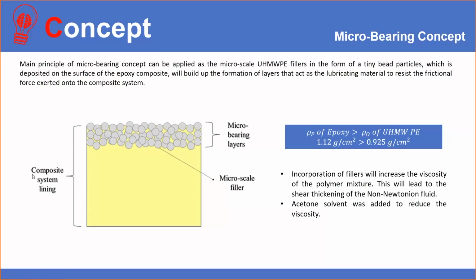So when the ultra-high molecular weight PE filler was incorporated into the epoxy resin, the situation where the density of epoxy resin, which is about 1.12 gram per cubic centimeter, is higher than the density of ultra-high molecular weight PE, which is around 0.92 gram per cubic centimeter, will encourage the microparticles of ultra-high molecular weight PE to accelerate upwards and float until it is partially submerged during processing before it undergoes the curing process, forming two distinctive layers.